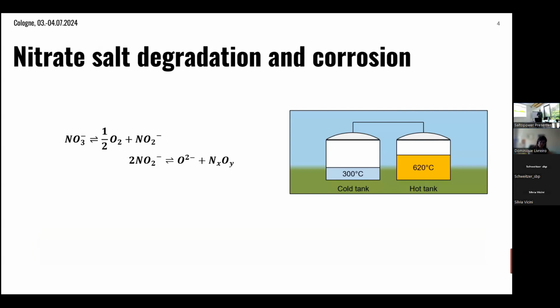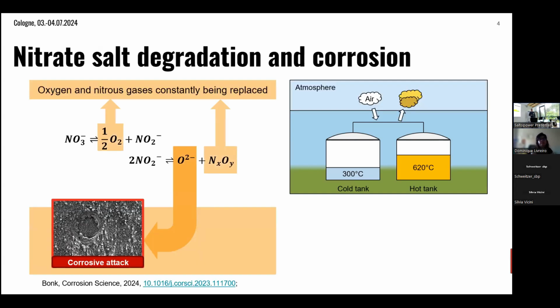So the first challenge: corrosion and degradation of salt. In this slide, you see there are two basic degradation reactions. The first reaction is nitrate to nitrite under the formation of oxygen, and the second reaction is nitrite to oxides and nitrous gas. If you increase the temperature, the equilibrium will shift to the right, and oxygen and nitrous gases are constantly being replaced in an open system.